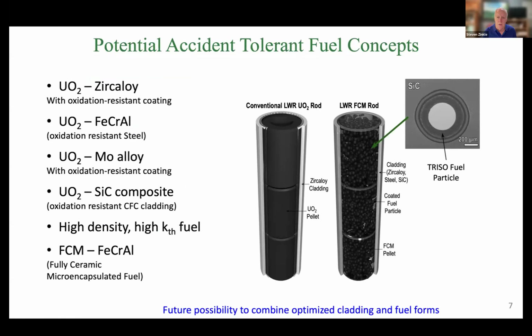It has a fuel kernel, and then a porous graphite layer, and then a silicon carbide pressure vessel layer, and then an outer graphite layer. In those multiple layers, the inner graphite layer can accommodate the fission gases that would be released during high burnups of the material, and then the silicon carbide pressure vessel keeps it from escaping out from that material.